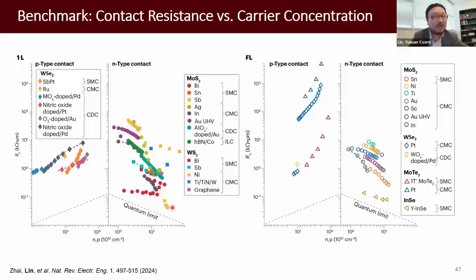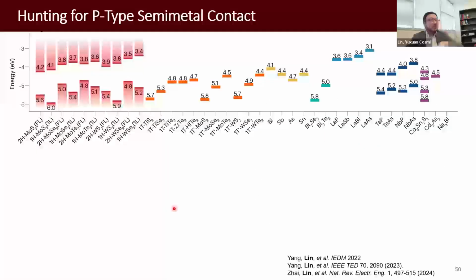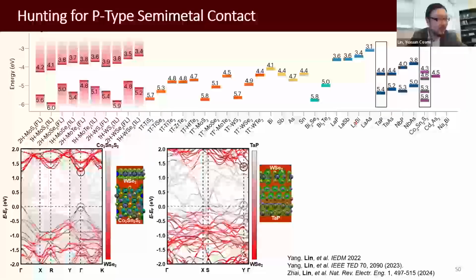So we also tried to use this theoretical approach to computationally screen which high work function semi-metal may be suitable to access the valence band for good P-type semi-metal contacts. And we focus on these two materials, tantalum phosphide and cobalt-tin sulfide. They have different surface terminations, so the work functions are also different, but we focus on the higher termination. And from the DFT calculation, we can see the metal-induced gap states are indeed suppressed.